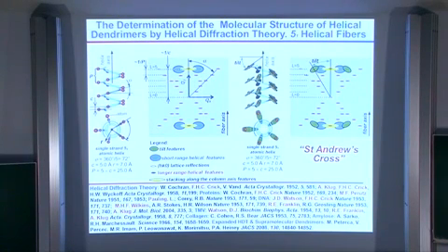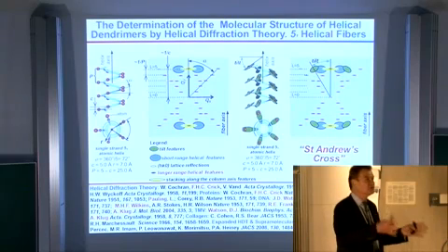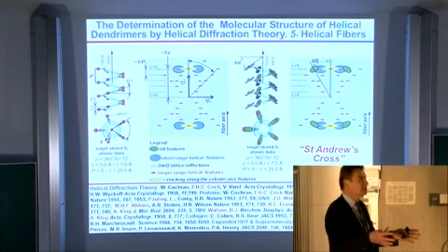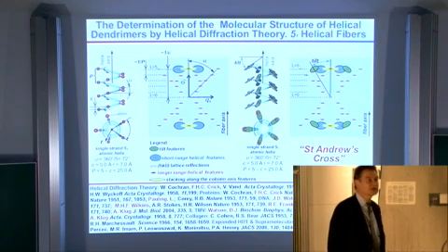That is the distance from the center of the helix to the high electron group of atoms that rotates to form the helix. The distance between these spots on the meridian gives you the pitch of the helix. That is the distance in between the high electron density spots. So with this story in your hands, you could have solved the double helical structure of DNA while being in kindergarten.